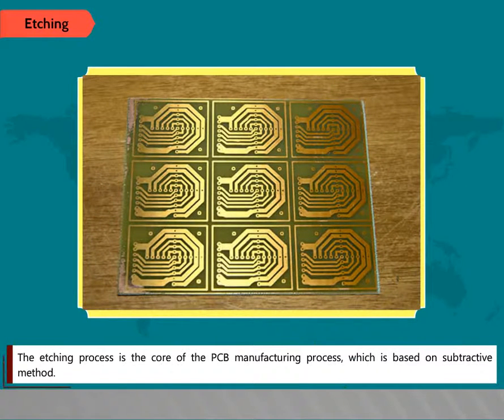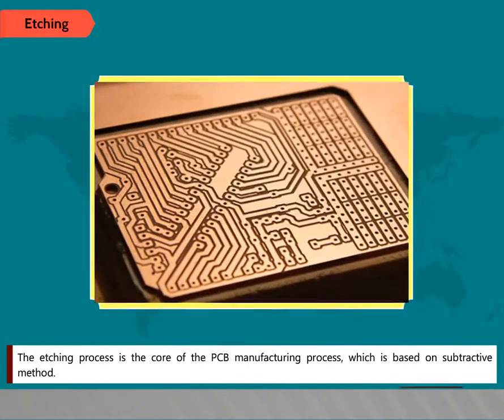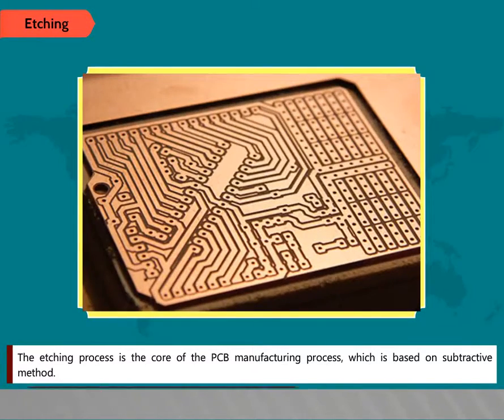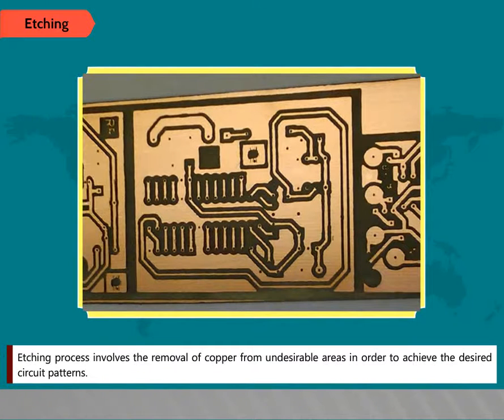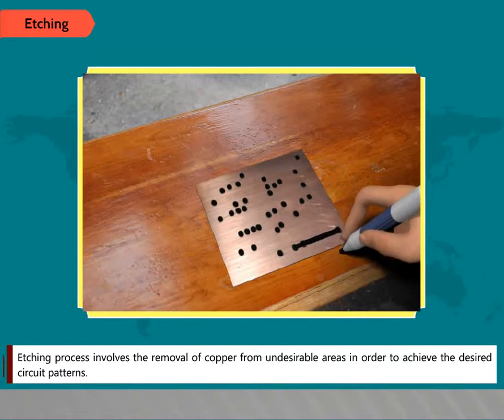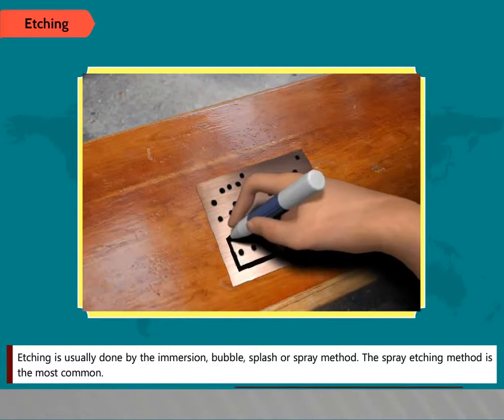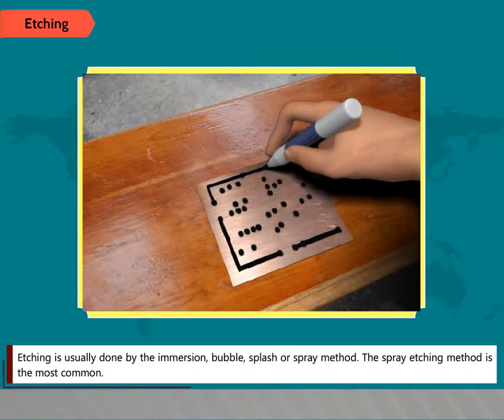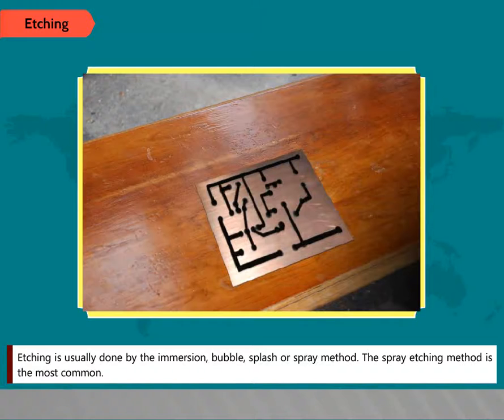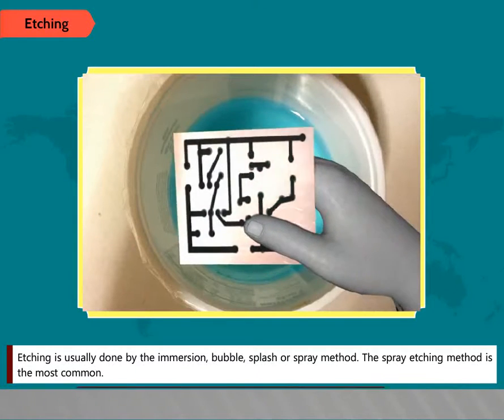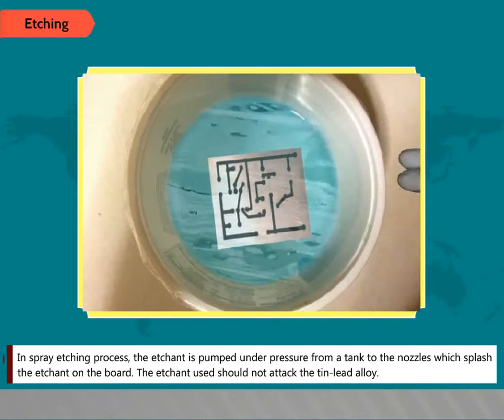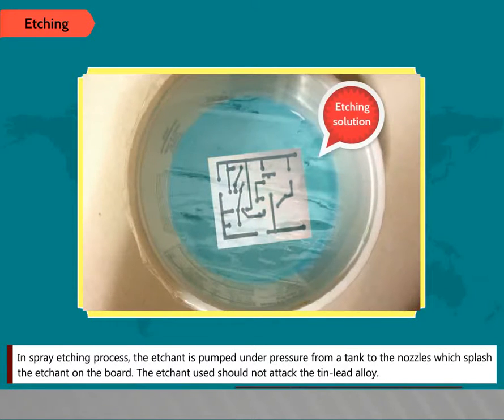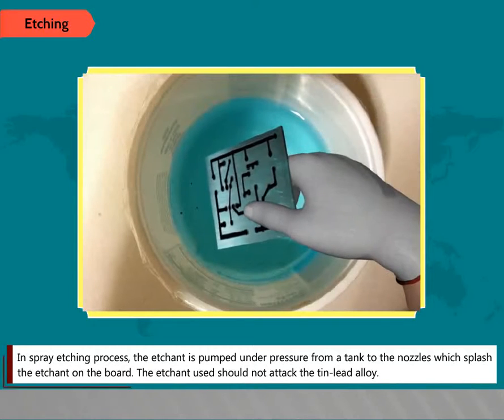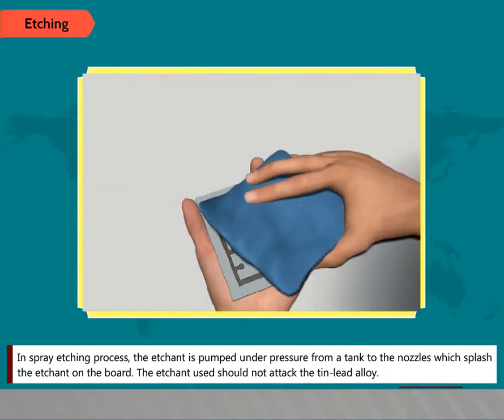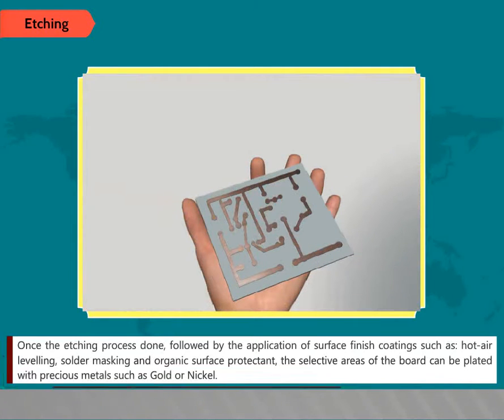Etching. The etching process is the core of the PCB manufacturing process, which is based on the subtractive method. Etching involves the removal of copper from undesirable areas in order to achieve the desired circuit patterns. Etching is usually done by the immersion, bubble, splash or spray method. The spray etching method is the most common. In spray etching, the etchant is pumped under pressure from a tank to the nozzles which splash the etchant on the board. The etchant used should not attack the tin lead alloy.